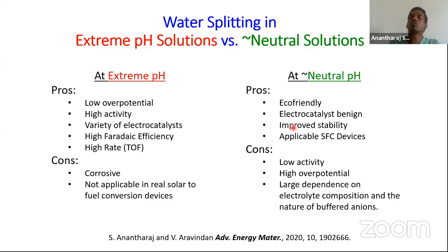So what are the advantages of doing water splitting in extreme pH solution is that they are almost ionic in nature. If you have pH 0, you have abundant proton, which means that you can perform hydrogen evolution reaction so easily. If you have very high pH, like extremely alkaline, when the pH is 14, you have abundant hydroxide, which means that you can easily perform water oxidation. So that is why people are sticking with either proton exchange membrane acidic water electrolyzer or anion exchange membrane alkaline water electrolyzer, which are so far the best ones for generating hydrogen from water in an energy efficient way.